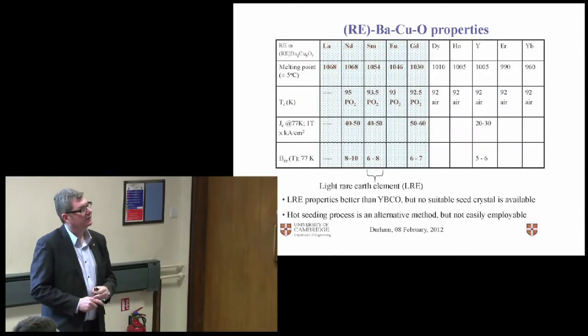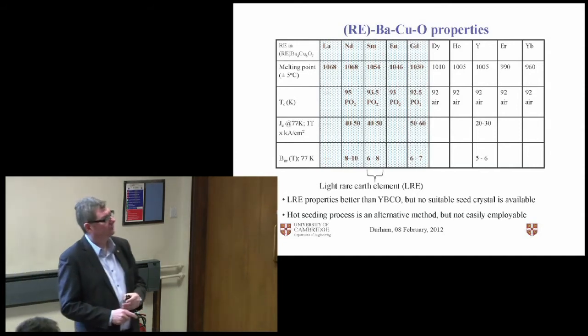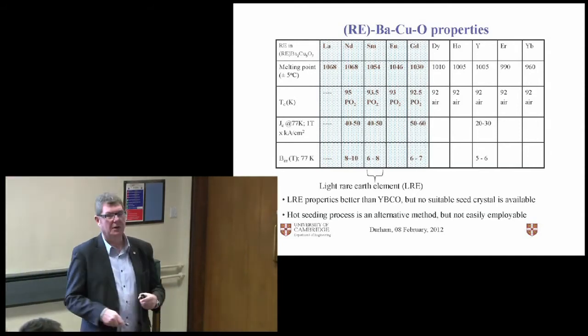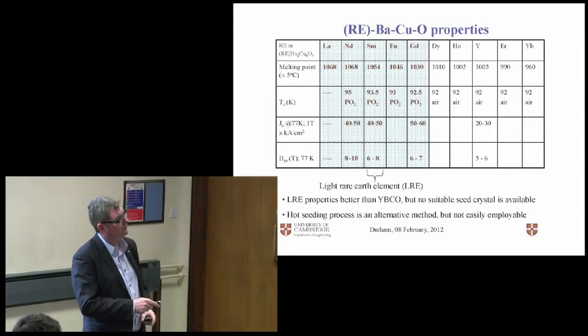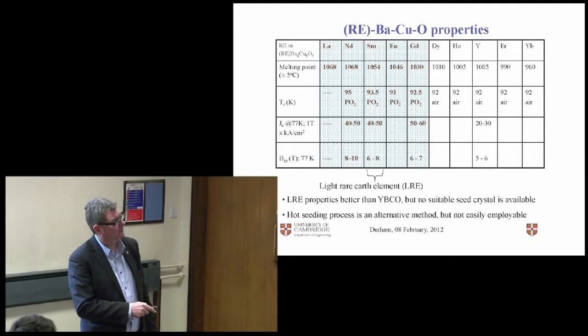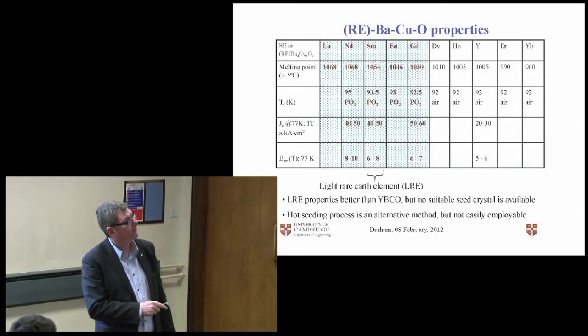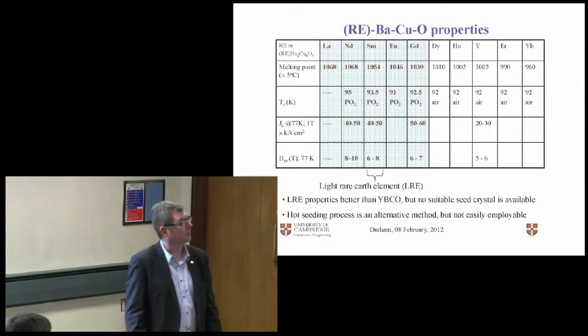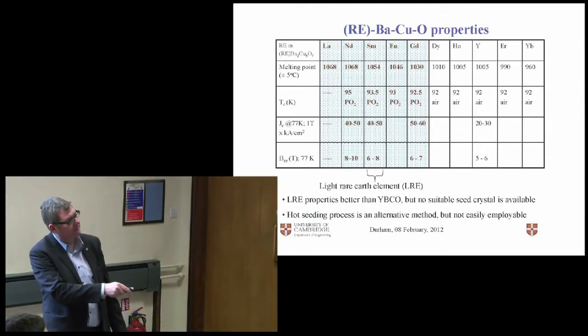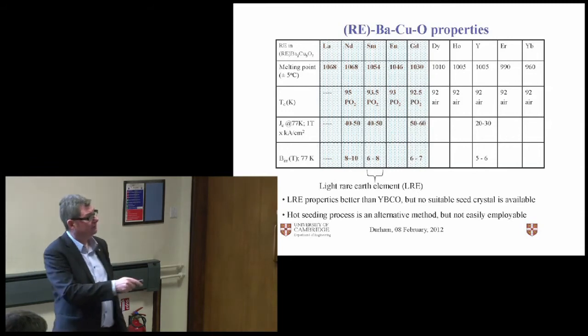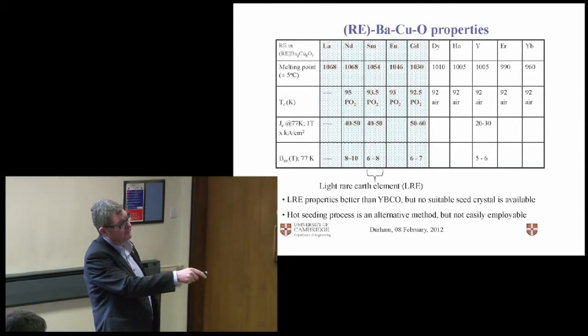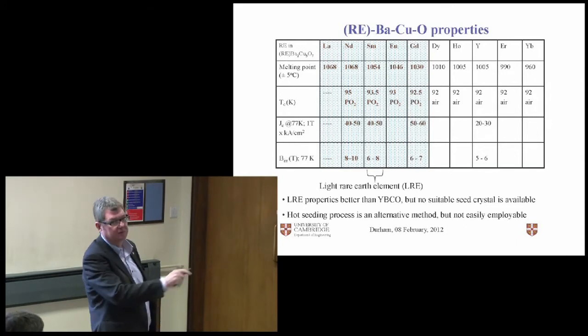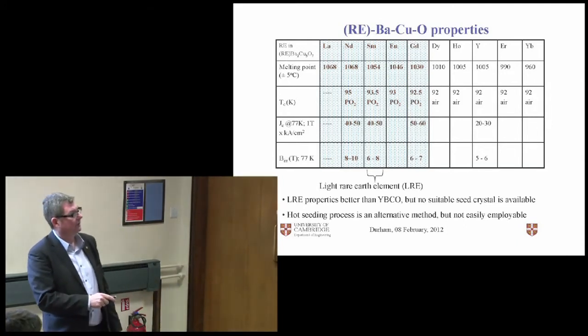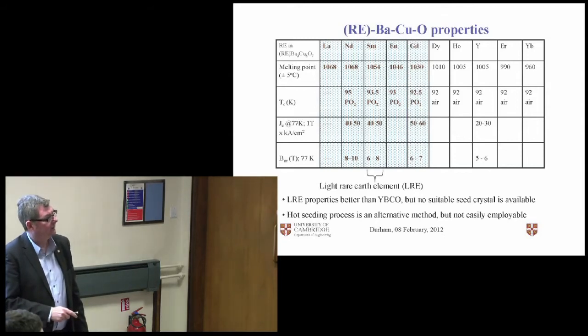Okay, so if we look at the different rare earth barium copper oxide materials available, the ones that are shaded light blue are the light rare earth elements, and they tend to give you better properties. So they give you higher transition temperatures, and they give you higher JCs, and they give you higher irreversibility fields. So you'd like to make lanthanum, neodymium, samarium, europium, or gadolinium barium copper oxide. If you look at yttrium, you get less good properties. However, the question is, you can seed yttrium with any one of these, but what do you seed these compositions with? It's not obvious. And there isn't an obvious seed available.